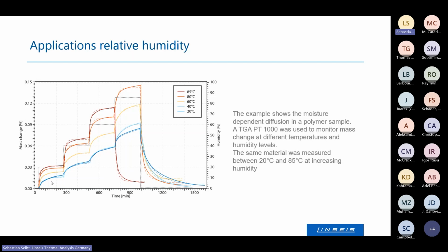What you see is that the mass increase of the sample at lower humidity levels is drastically lower than at higher humidity levels. So at higher humidity level, the polymer takes up much more weight, so it takes up much more of the humidity from the atmosphere.